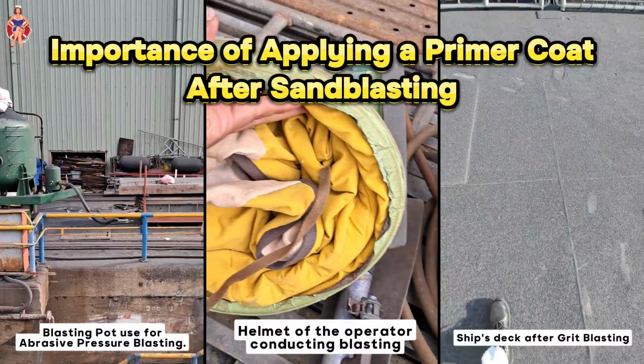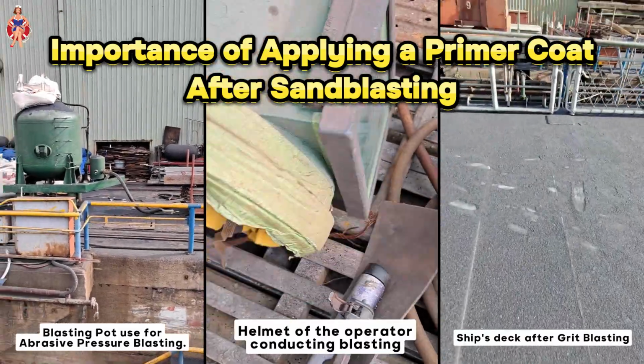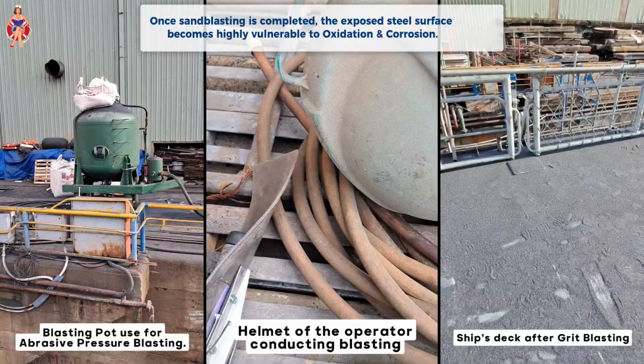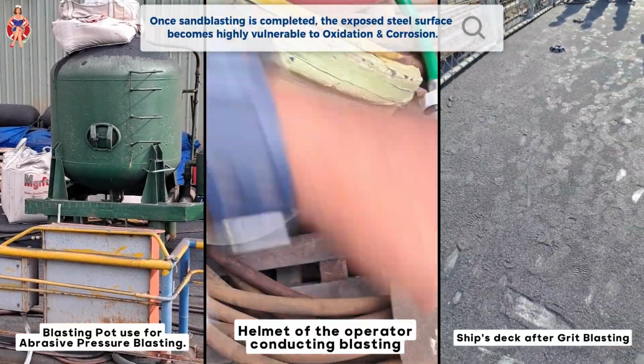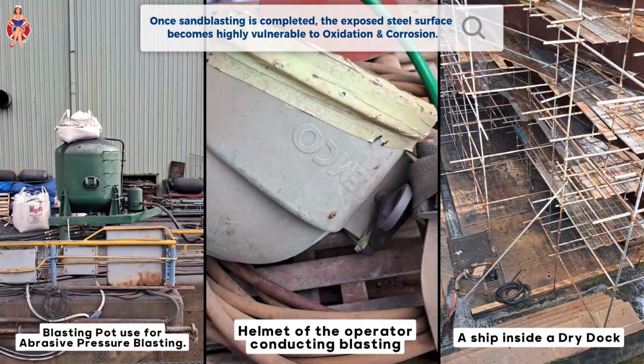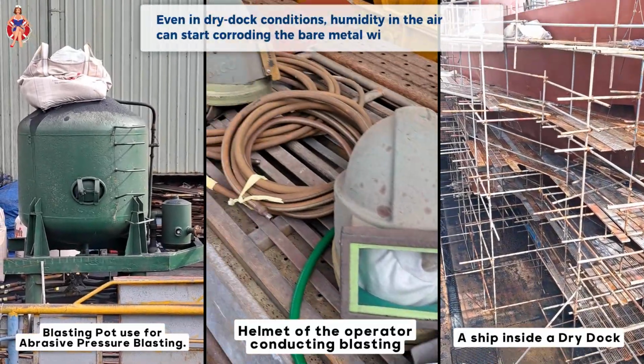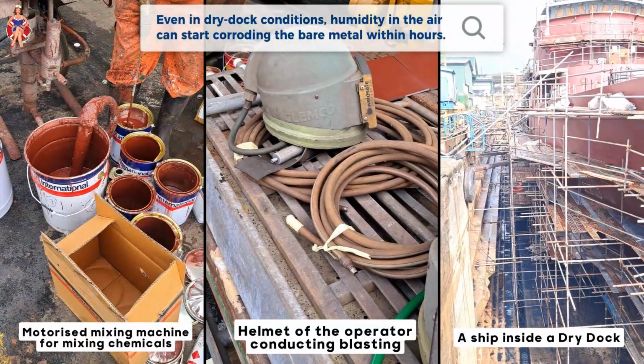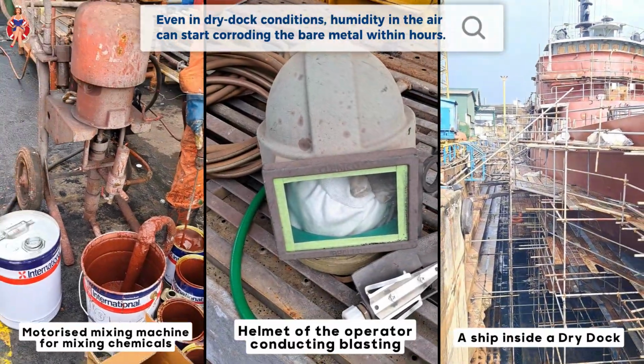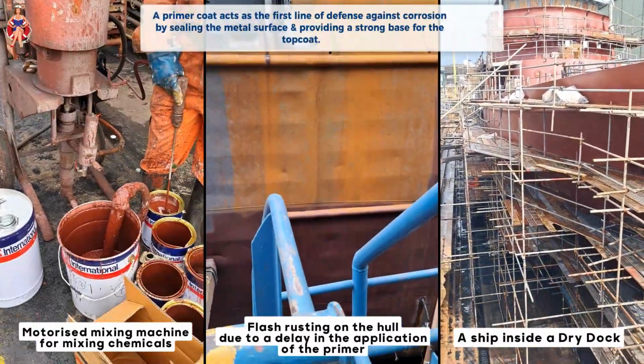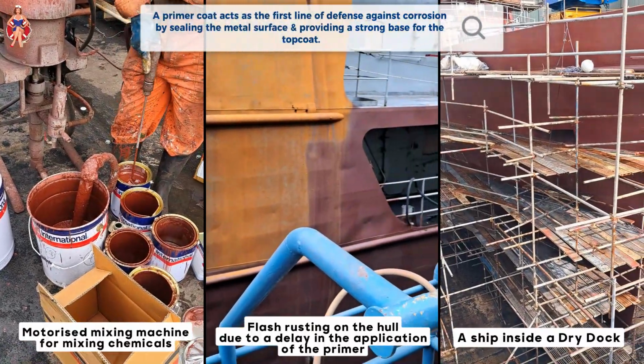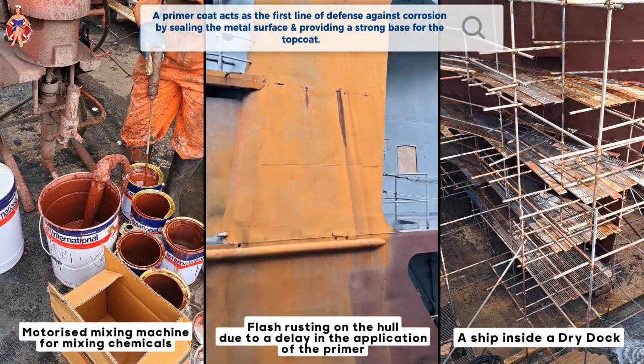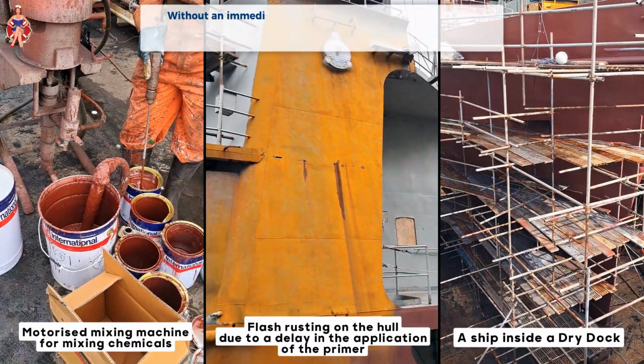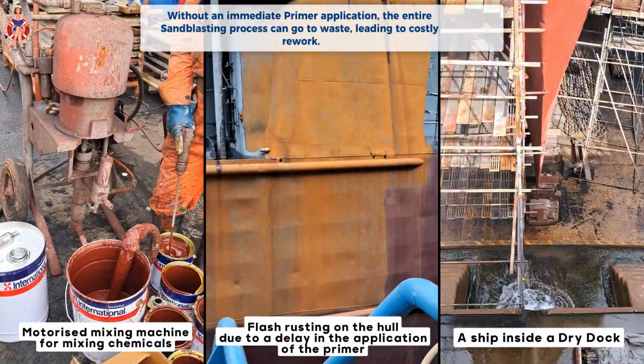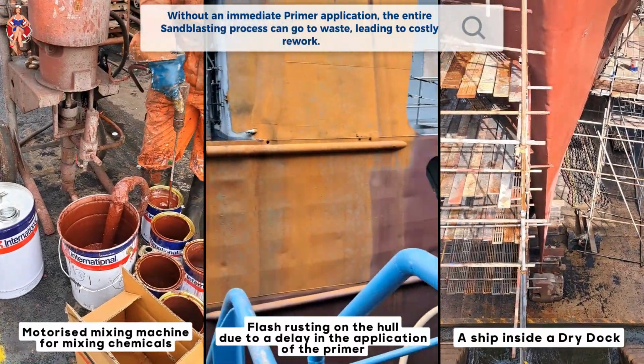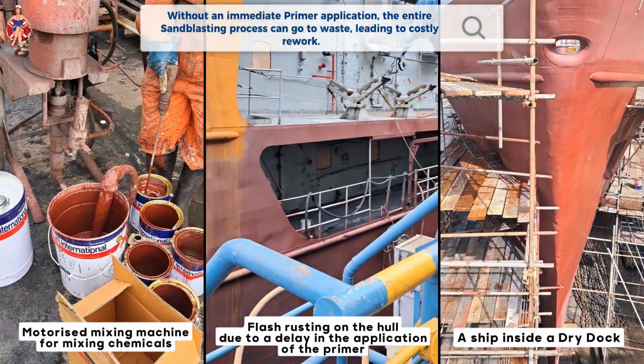Importance of applying a primer coat after sandblasting. Once sandblasting is completed, the exposed steel surface becomes highly vulnerable to oxidation and corrosion. Even in dry dock conditions, humidity in the air can start corroding the bare metal within hours. A primer coat acts as the first line of defense against corrosion by sealing the metal surface and providing a strong base for the top coat. Without an immediate primer application, the entire sandblasting process can go to waste, leading to costly rework.